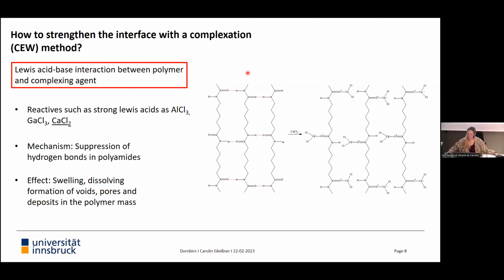And what's actually happening? In a non-treated polyamide 6,6 fiber or polymer, you have these polyamide chains with their characteristic structure unit here. So you have the amide group, and the polymer chains will arrange themselves so that the formation of hydrogen bonds can occur at its maximum. So that the oxygen atom from one polyamide chain can form a hydrogen bond with the NH group of another polyamide chain.